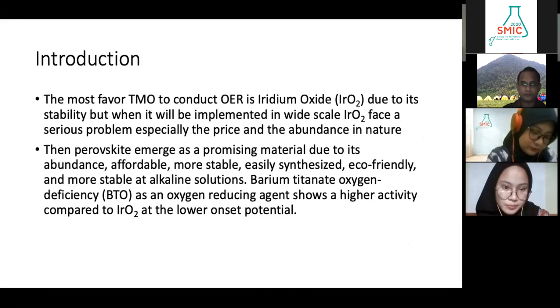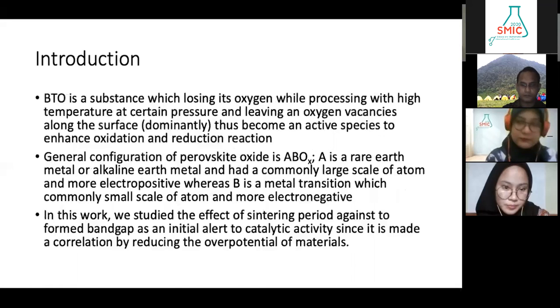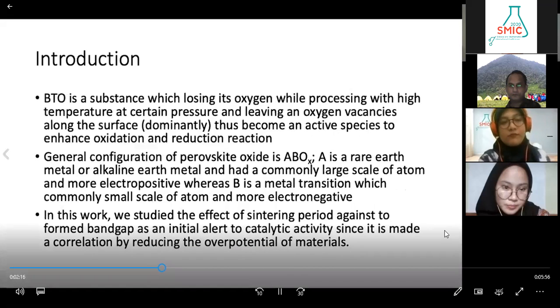Then perovskite emerged as a promising material due to its abundance, affordability, easy synthesis, eco-friendliness, and stability in alkaline solution. Barium titanate with oxygen deficiency, known as BTO, as an oxygen-reducing agent, shows a higher activity compared to iridium oxide at a lower onset potential. BTO is a substance which loses its oxygen when processed at high temperature at a certain pressure, leaving oxygen vacancies along the surface, which then become active species to enhance oxidation and reduction reactions.